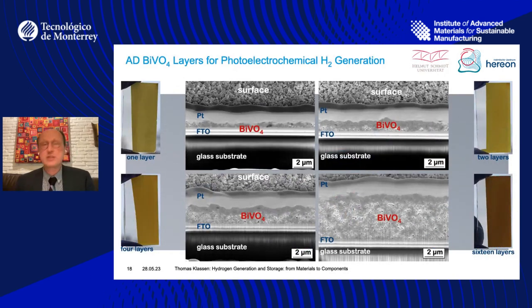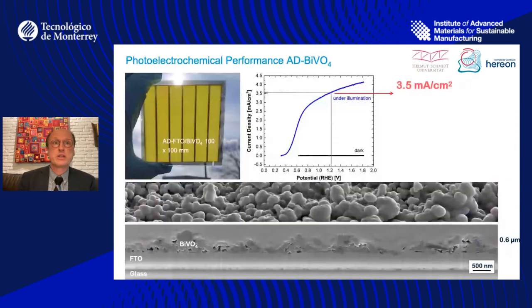So here you see bismuth vanadate in different thickness. This is actually always the coating on FTO and on the glass substrate, as you have seen before. And we can produce larger specimens. So this is about 10 by 10 centimeter coatings that we can put in the devices. So here you see an example.